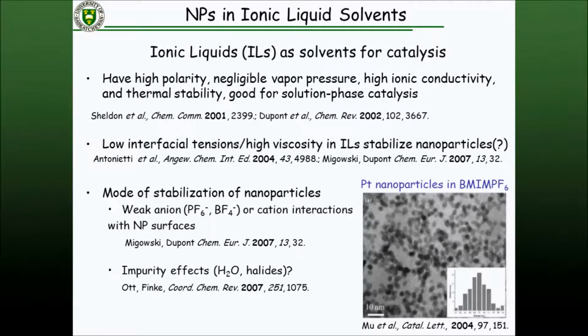That negligible vapor pressure is a double-edged sword because it also means you can't purify it as you do most solvent. Right? We normally think about solvent stills and purifying solvent by distillation. That's not possible for many ionic liquids. But there's this idea then that these are essentially, if you will, many of them are surfactant solutions really. But you get very low interfacial tensions, very high viscosities for some ionic liquids that may help stabilize nanoparticles.